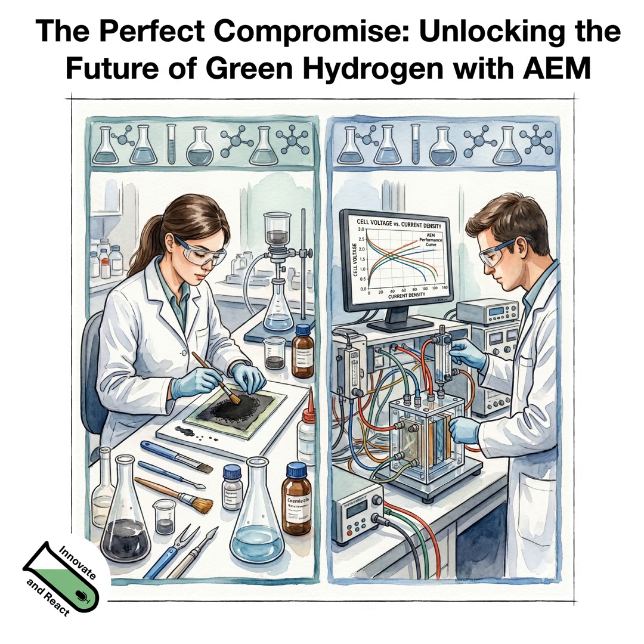Yeah, and regarding the stability, we do the long-term measurement, but to really understand why these materials work or are stable or are not stable in our system, it's also important that we analyze the used materials and then ask ourselves, okay, what is the real active site, and why is the system running, or why does my material degrade during operation? And this is also something we try to work on to compare.